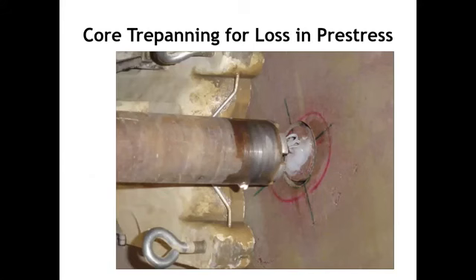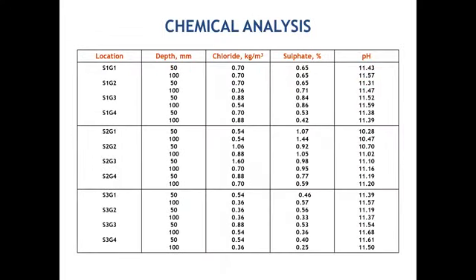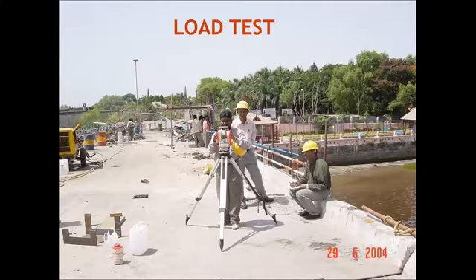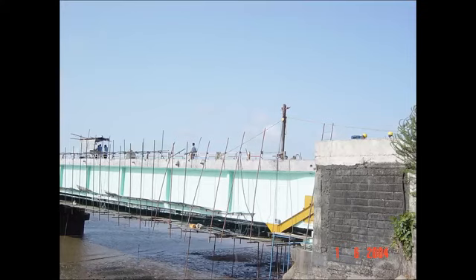As we said, the core trepanning method was adopted by SCRC to find out the loss of pre-stress, because there we cannot go for straightforward core extraction. Based on that, they analyzed the loss in pre-stress. Chemical analysis was done for chloride and sulfate. The chloride, you can find, is a little higher than the threshold limits in a few locations, and other locations are well within the limit. Finally, as it is a pre-stressed bridge, external pre-stressing was adopted as the rehabilitation methodology. Later the load testing was done, and it was certified for putting into use.